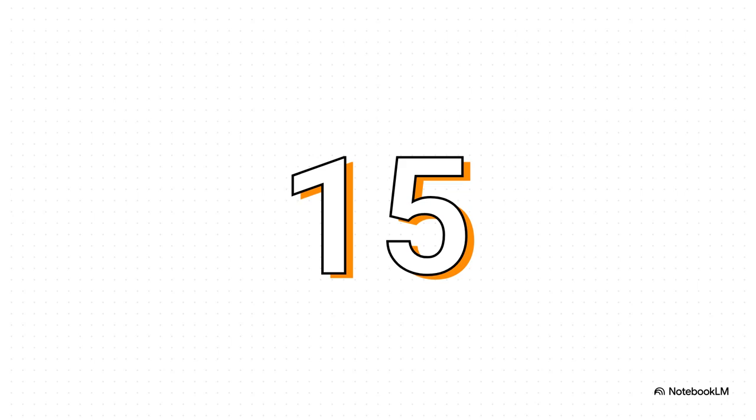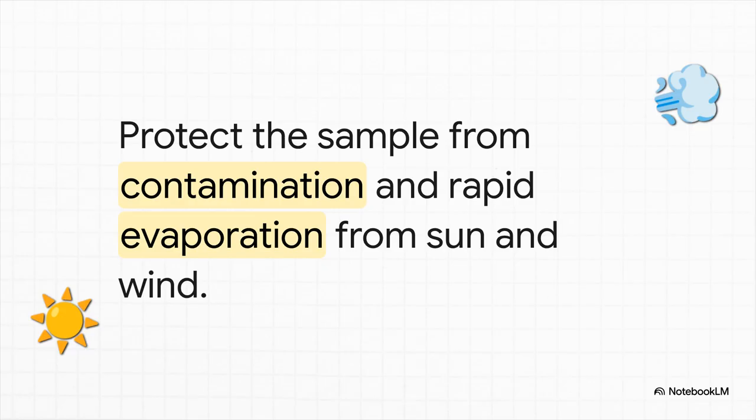15 minutes. This is your second and final deadline. It starts at the exact same moment as the first one. You have a total of 15 minutes to begin making your cylinders or beams. So the two numbers are 5 minutes for the initial tests, 15 minutes for the strength specimens. You gotta know them. And during this whole 15-minute window, you've got another crucial job.